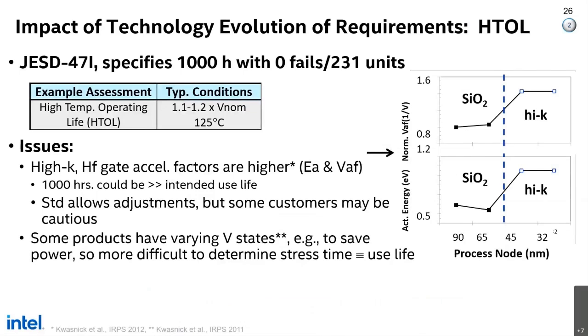Okay. So here is a case where we have a silicon process that was changed, and we didn't pass the 1K hour of HTOL, which is a standard from let's say 20 years ago. However, the lifetime that we estimated was 2 to 3x the lifetime of the legacy product. The reason this was different is because the voltage acceleration and activation energies were different.